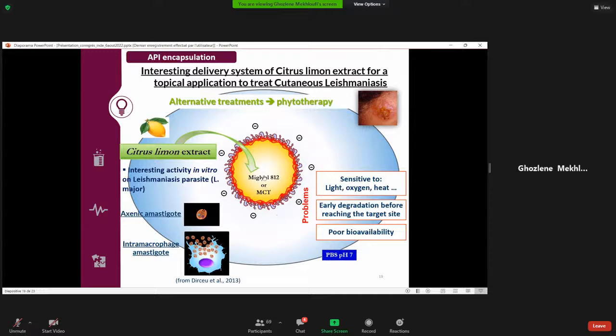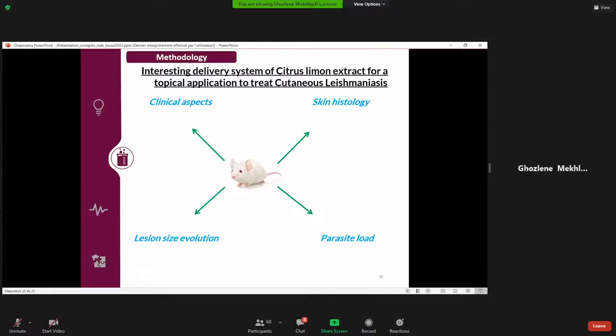However, it is known that plant extracts present some problems, such as low aqueous solubility and poor bioavailability. They are sensitive to light, oxygen, and heat, and they can degrade early before reaching the target site. That's why we thought to formulate the citrus extract, and we chose nanoemulsions as drug delivery system. These systems, extracts encapsulated in nanoemulsions, were tested in vivo on an animal model, and we checked many parameters such as clinical aspects of lesions, the lesion size evolution, the parasite load, and the histology of infected skin.